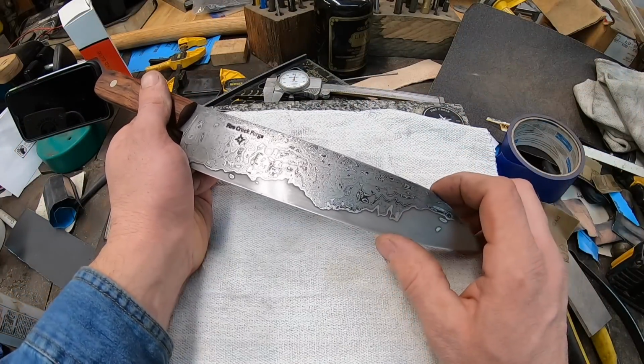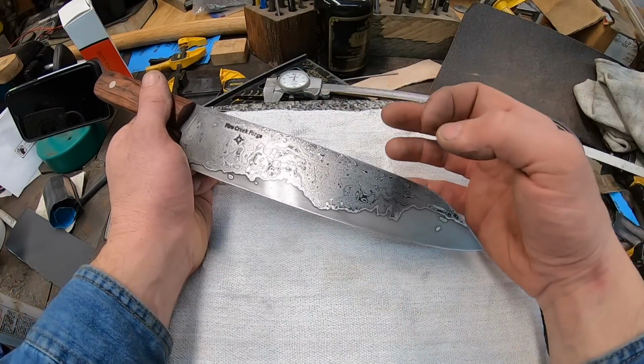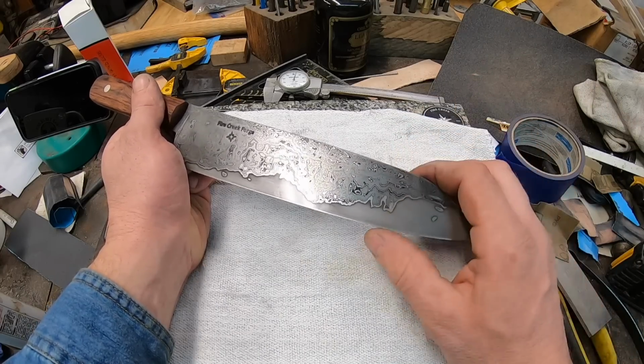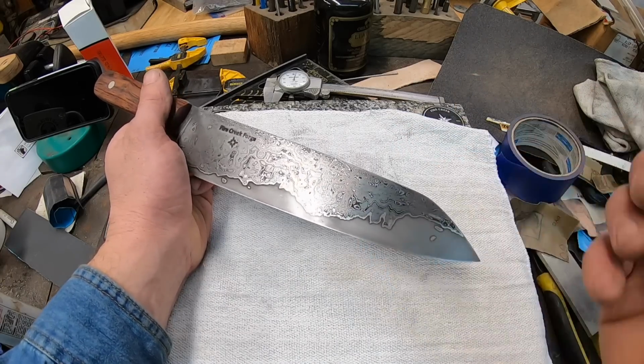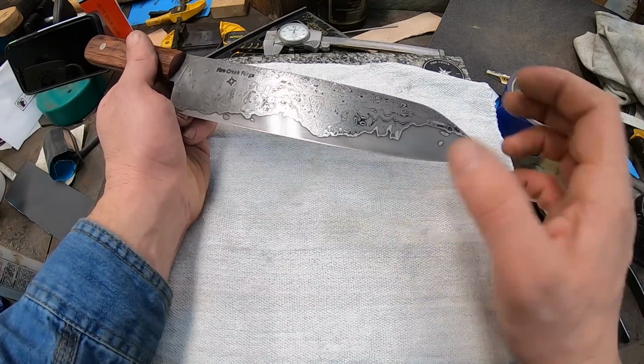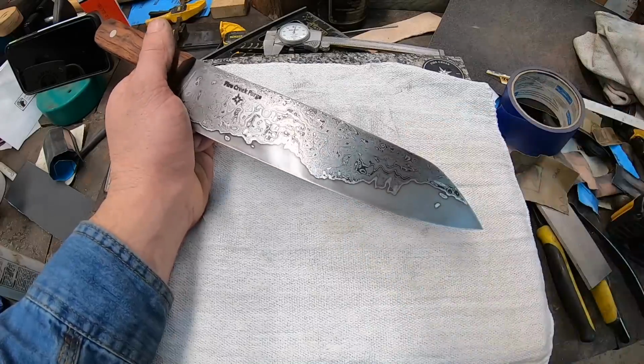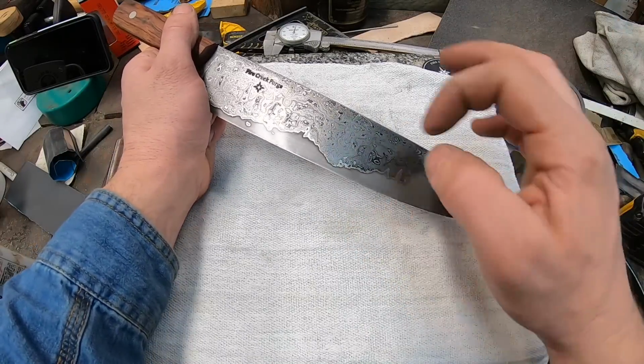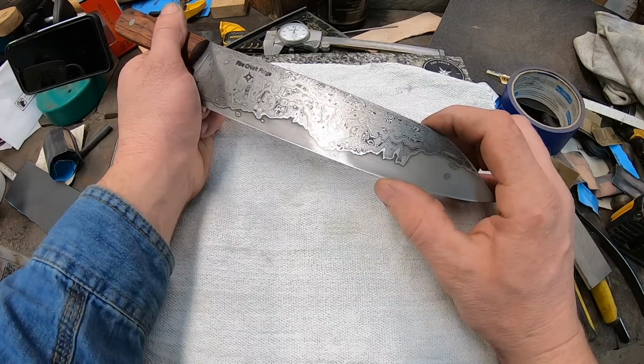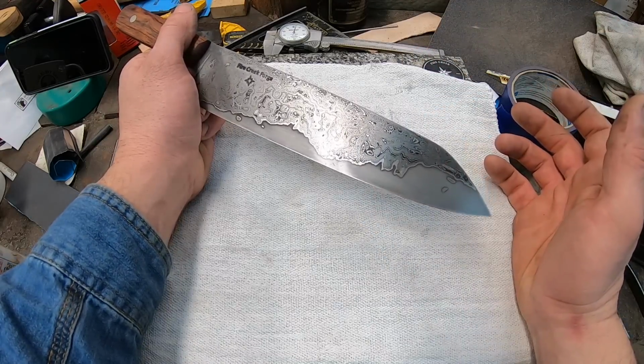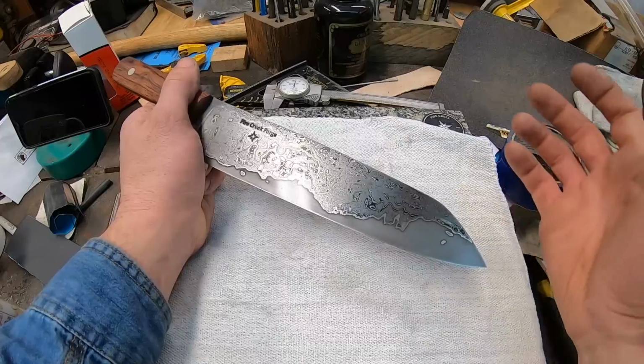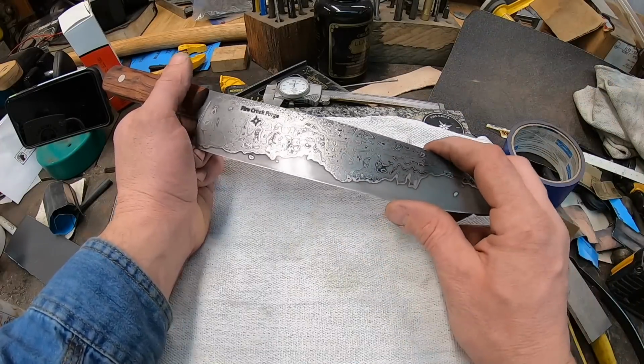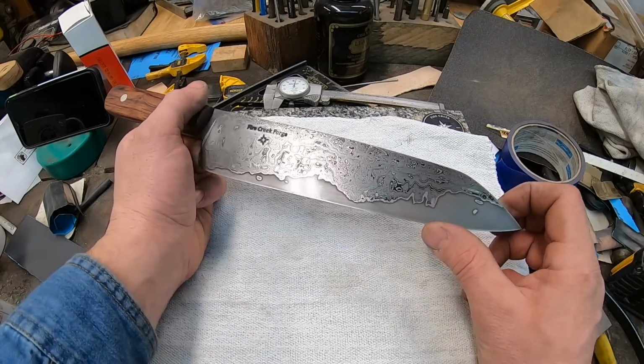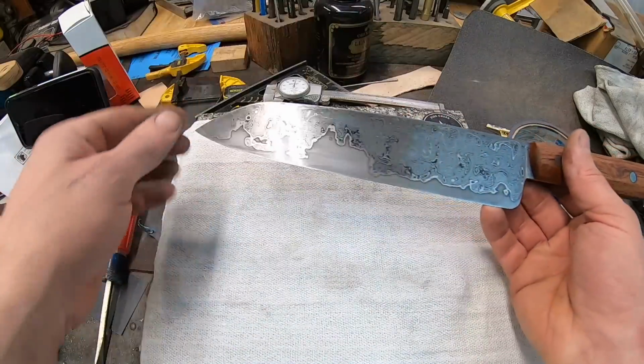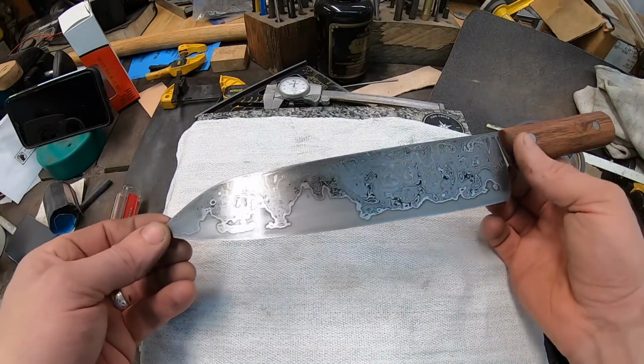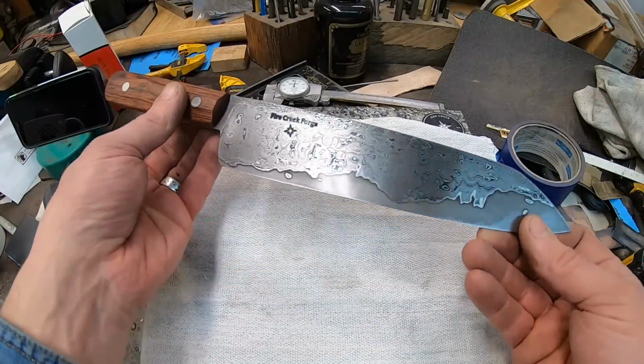And I think the fact that it was nickel and also that lower carbon steel, that 1045, it does not resist the forging like the high carbon does, and you really notice that when you're working with it. It feels like butter, but it's going to deform more and really kind of squish that together more than you would, say, on a 1095 and 15N20 layered steel billet. So lots of little things that you don't think about necessarily, and some of these I did think about but did not quite execute like I was hoping. So it's a great opportunity to learn from and do better the next time.